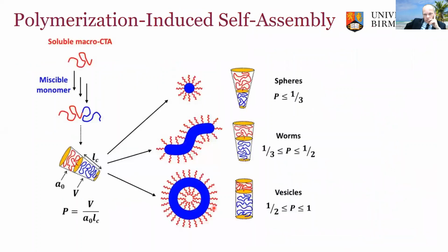So just to outline polymerization-induced self-assembly in case people aren't necessarily familiar with it, the concept is that you start with a soluble macro CTA and you polymerize a miscible monomer. That monomer, as you polymerize it, goes from hydrophilic to hydrophobic, and then during the polymerization process self-assembly occurs, hence the name polymerization-induced self-assembly. You form an amphiphile with hydrophilic and hydrophobic blocks, and those block ratios and packing parameters determine the morphology of the construct that you obtain, be that spheres, worms, or vesicles.